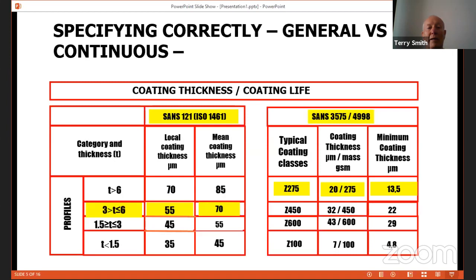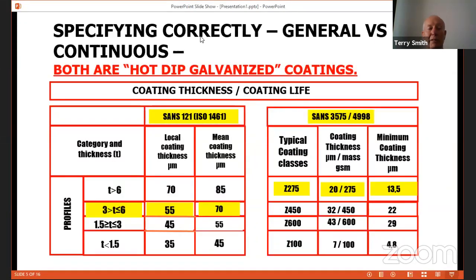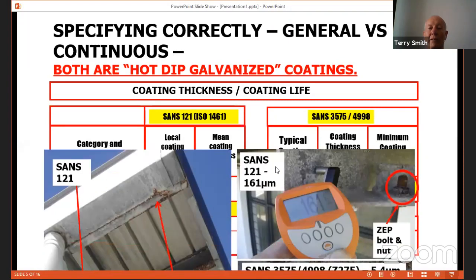Here's a comparison between two different specifications, one general and one continuous. Both are known as hot-dip galvanized coatings. What I've done is I've taken the incidence of SANS 121, which is the general galvanizing spec, and I've taken a profile of 3 millimeters or less than 6. You can see the local coating thickness is 55 and the mean is 70 microns. If you look over this side under the continuous galvanized, I've got Z275, which is a nominal coating of about 20 microns and a minimum of 13.5. Compare those things in a site.